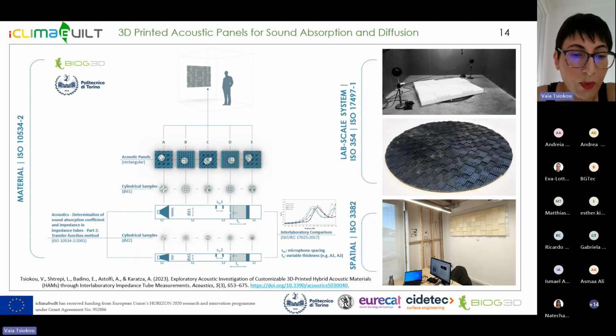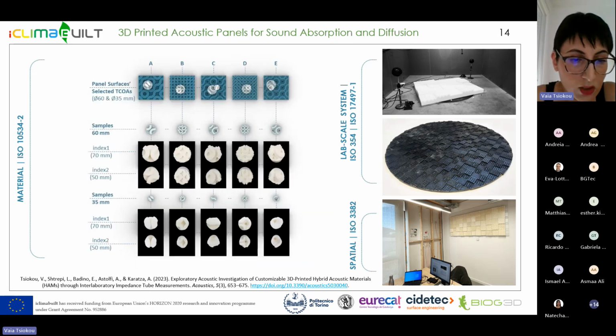To conclude, the proposed design methodology paves the way to a customizable large-scale cumulative acoustic performance by varying the parametric step thickness. An interlaboratory study with Polito helped us address the challenges on a material level analysis in an impedance tube with respect to the representativeness of the test samples and their relevance to the original panels. And further testing involves analysis of absorptive and diffusing properties in a small-scale reverberation chamber and in-field measurements in living laboratories according to the respective standards.